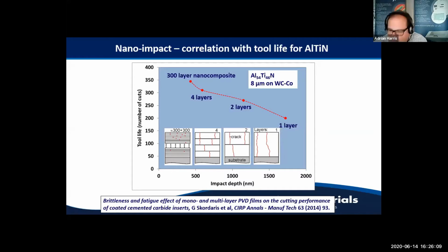Yep. In the case of the monolithic coating, there are none of these interfaces present between the individual layers, and so the cracks can grow rather uninhibited all the way down to the substrate. And intermediate samples here have got different numbers and thicknesses of individual layers. So the structure of a coating is important as well as just the composition.